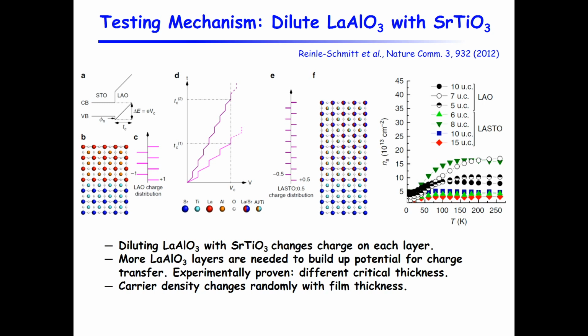But if you grow the diluted film, then each layer is carrying only, in this case, it's 50-50 lanthanum aluminate versus strontium titanate, then it carries +half and -half of charge. And the divergence of this field becomes slower. So this will lead to a different critical thickness, which this report has observed. Right? So that's good. That is kind of supporting the idea that you do need this divergence